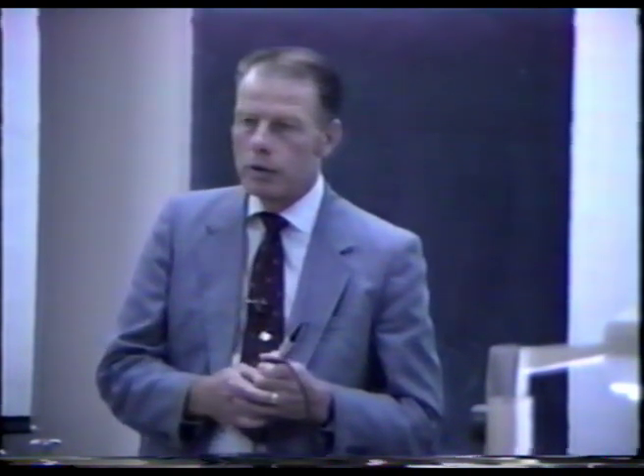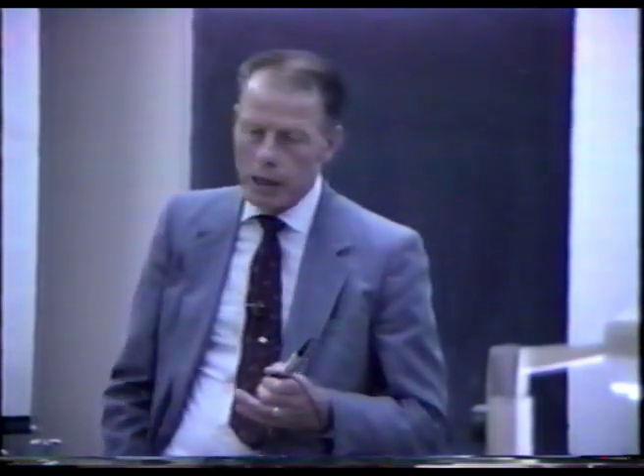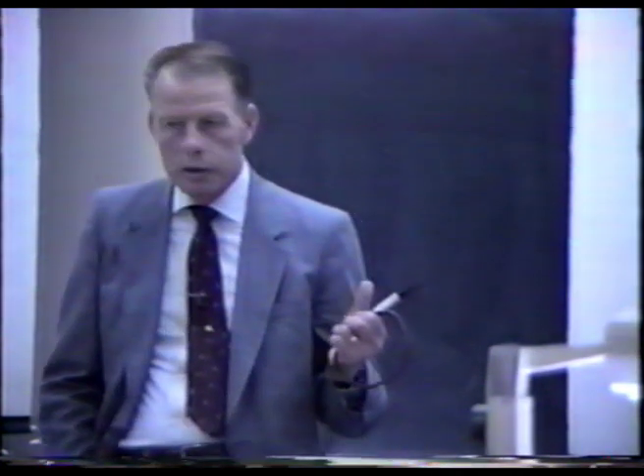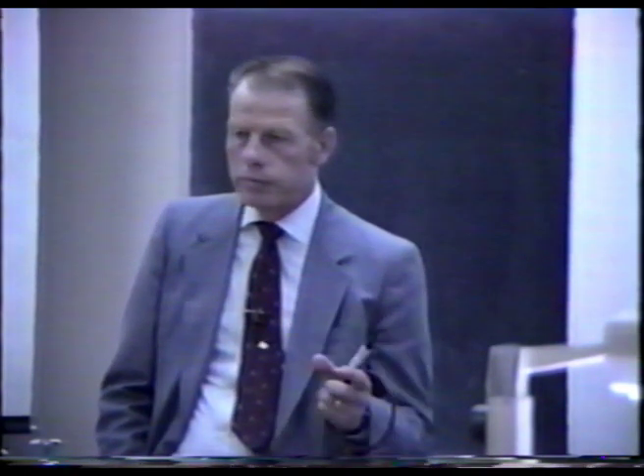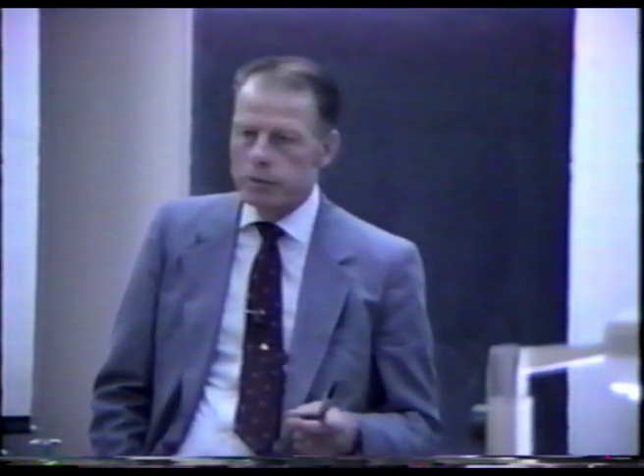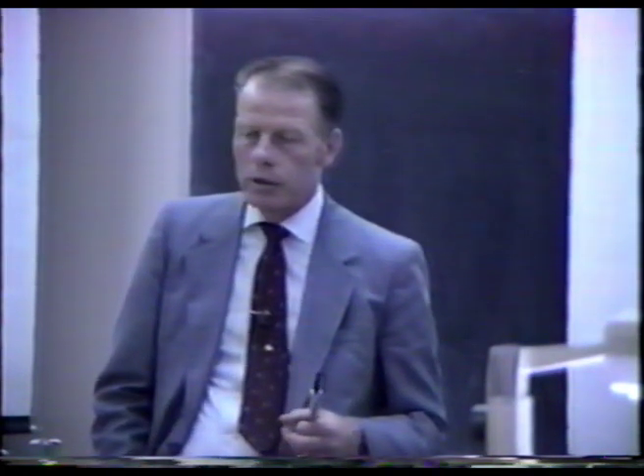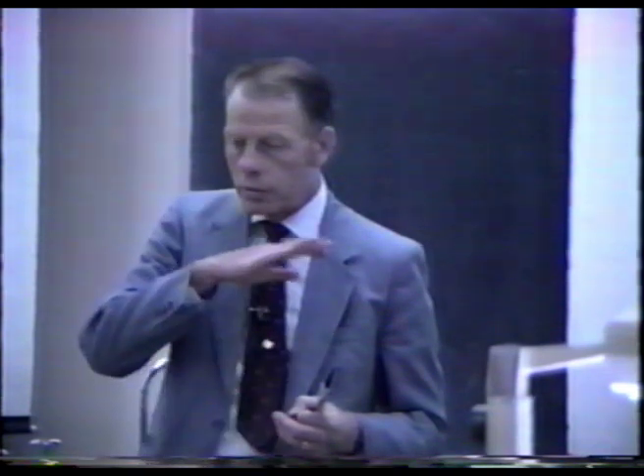Right. But other people have claimed that when they add D2O, sometimes they trigger an effect too. So just like the Takahashi experiment, running at steady state is not necessarily a good thing. Adding D2O, that's a drastic change to your system. It's a sudden change in voltage. That can also be a triggering effect and help produce an excess heat effect as well. And we've seen that sometimes. Adding D2O seems to trigger an excess heat effect as well. That goes back to Takahashi's method, where you don't want to keep everything at steady state.